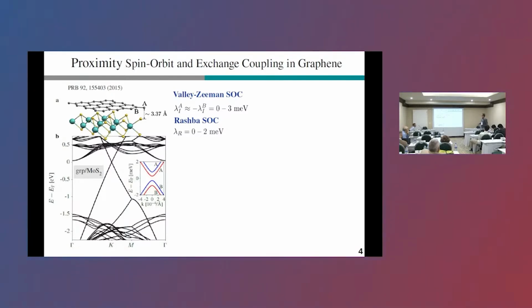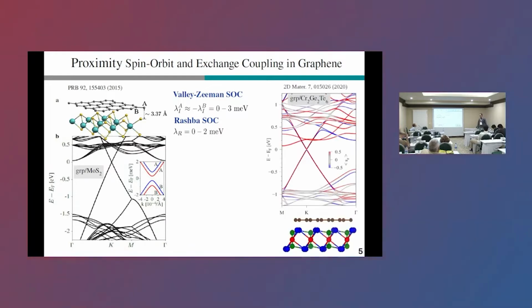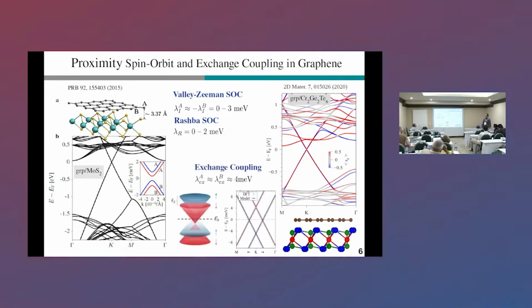Now, another spin interaction that can be induced in graphene is, of course, the exchange coupling. So when you place graphene on chromium germanium telluride, for example, which is a ferromagnetic semiconductor, you will find a very similar situation. The Dirac states of graphene are quite nicely preserved within the band gap. If you then zoom in to the Dirac states, you will find such a splitting of the bands, which reminds us of the Zeeman splitting from an external magnetic field. But here it is not an external magnetic field, it's rather the exchange field originating from the ferromagnetic semiconductor.